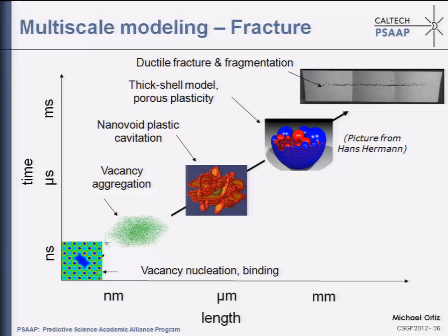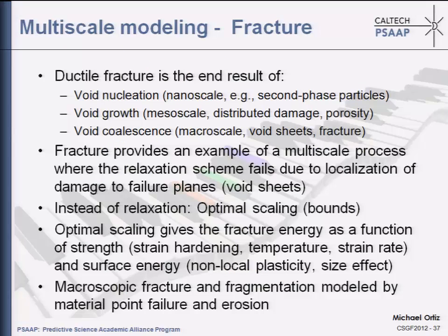Specifically, this step where you go from distributed damage to localized damage is something that is not amenable to the kind of upscaling that I described earlier, because that upscaling, as I said, avoids nucleation, growth and coalescence. And fracture provides an example of a multiscale situation where, because the damage becomes localized to a plane, it's no longer just a representative volume kind of situation. It's not about volumetric averaging, but to get at the fracture properties of the material, you have to allow for localization of damage to individual fracture planes, what are known as void sheets.